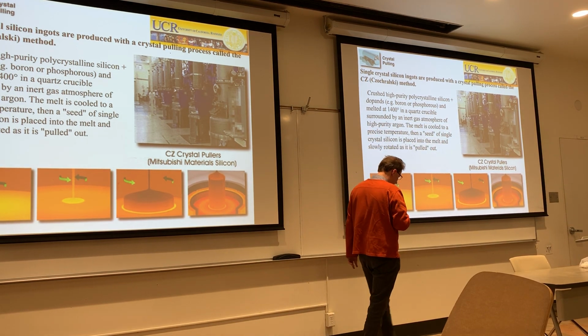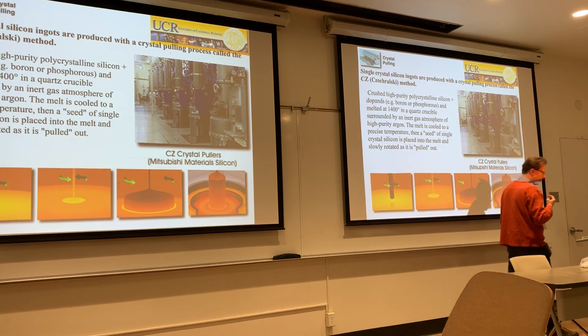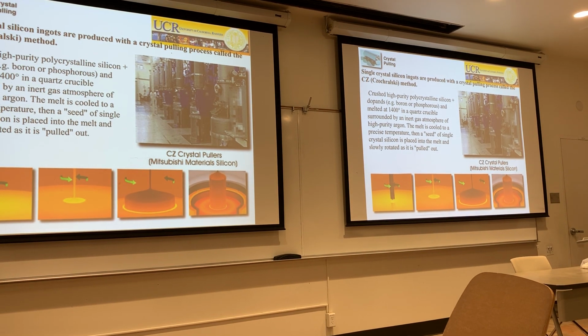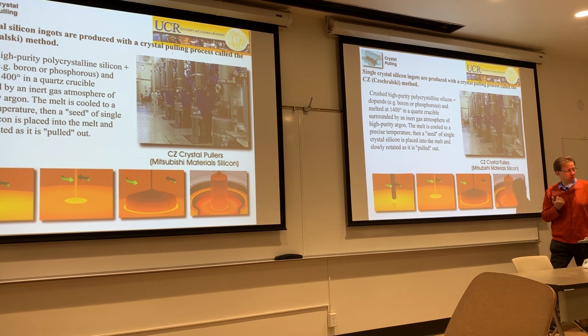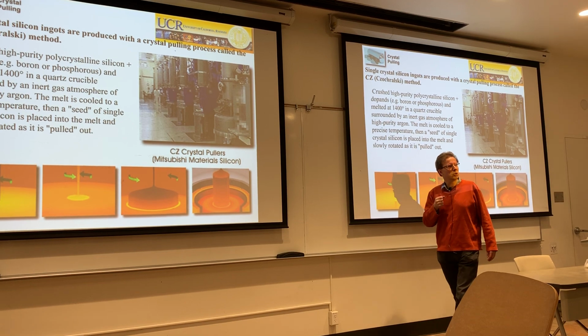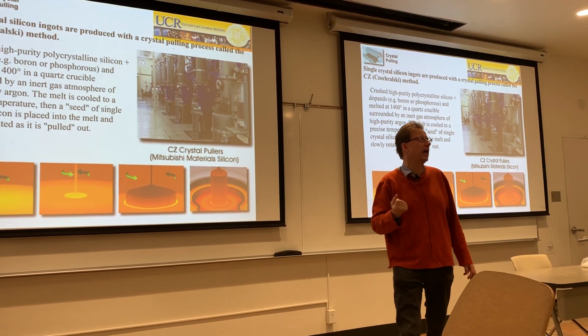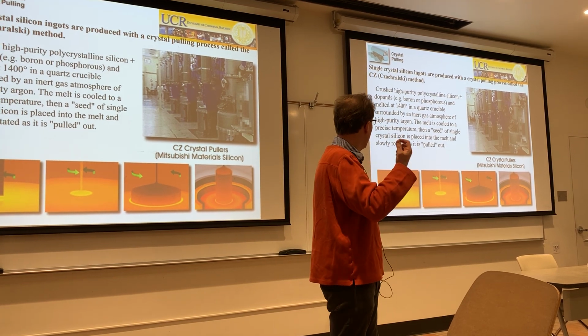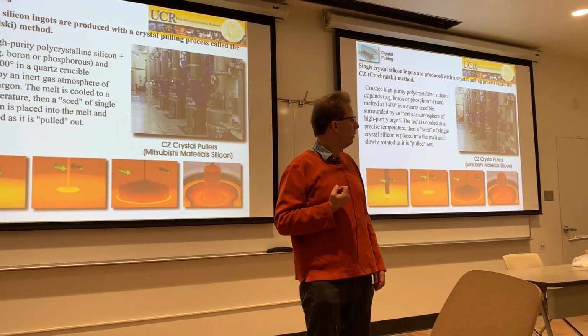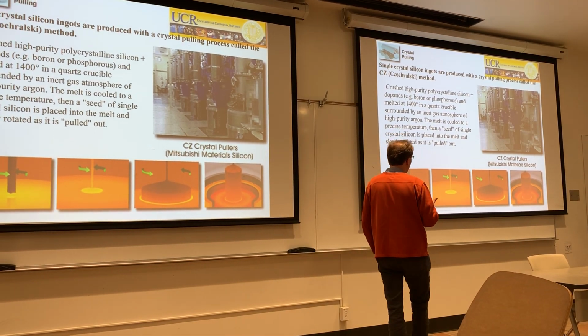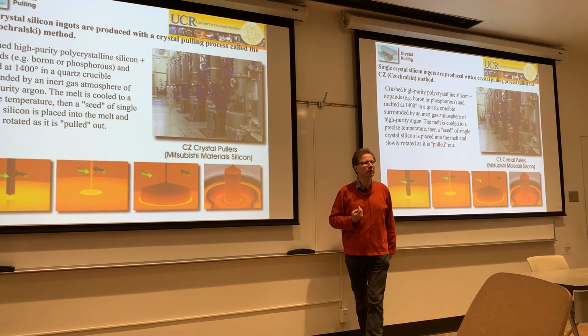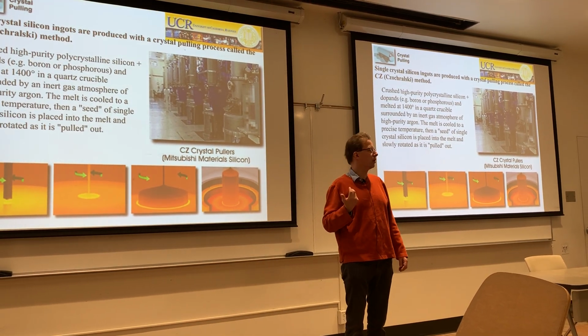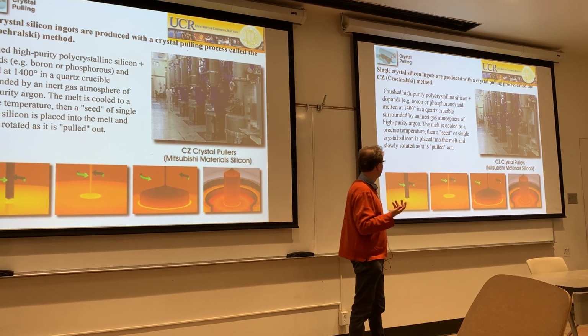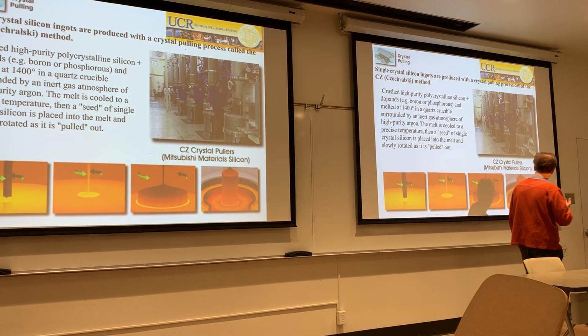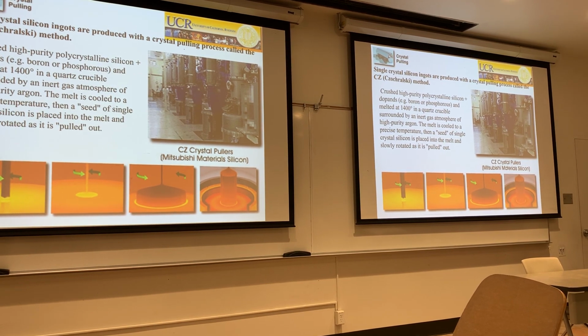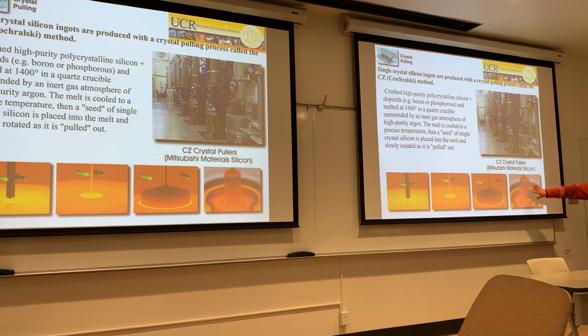Now it's a really complicated process because you look at purities of materials. The dopant concentrations which we were talking about are on the order of 10 to the minus 6. So you need to have 6 nines purity in order to have controlled doping. Really, you need to have 8 or 9 nines purity in the silicon, so that you have a well-defined dopant concentration there. Which gives some problems, because it means now that all the surfaces of your crucible over here must not leach out any of the elements in that. You must make sure that there's no oxygen or other elements coming through the gas phase. It is a really complicated process. And you want to have a constant dopant concentration in your ingot.